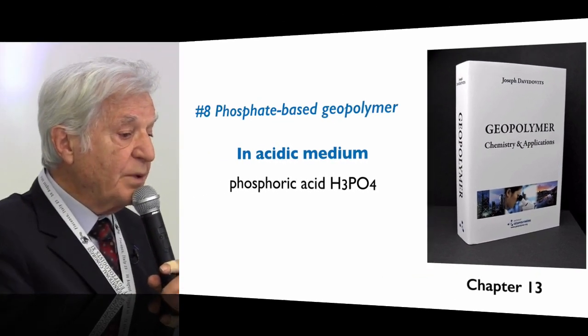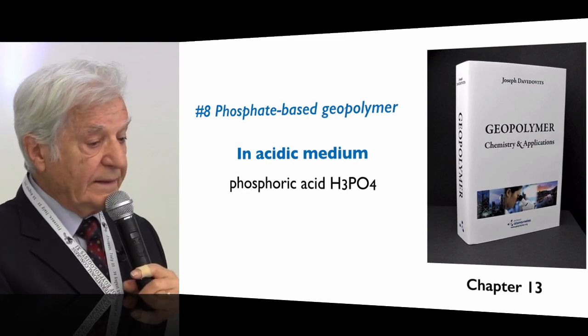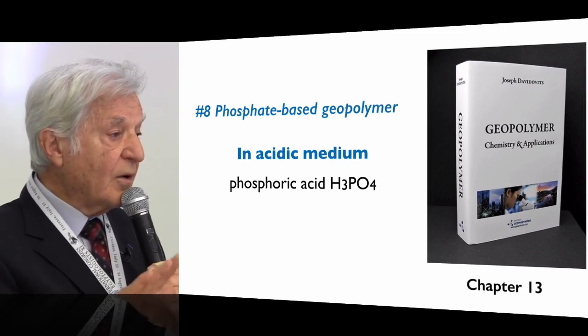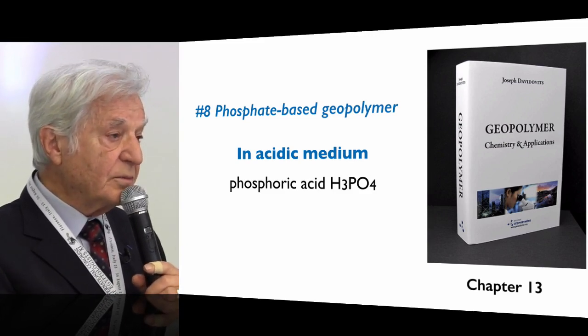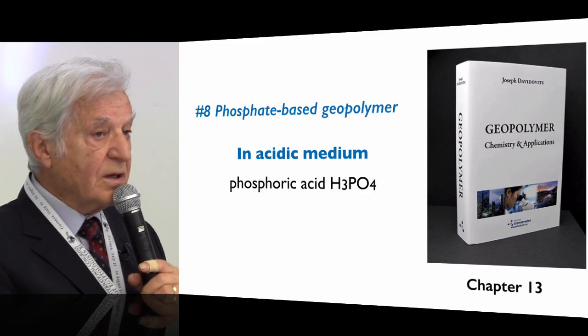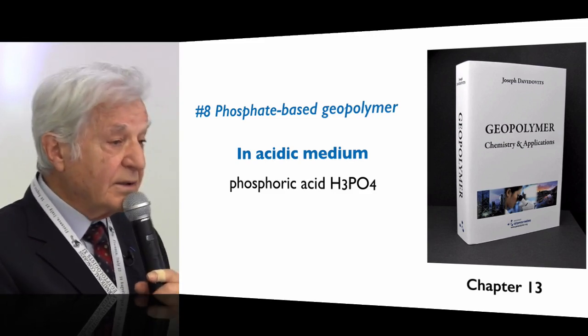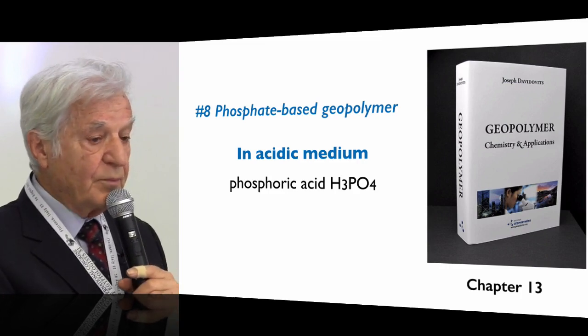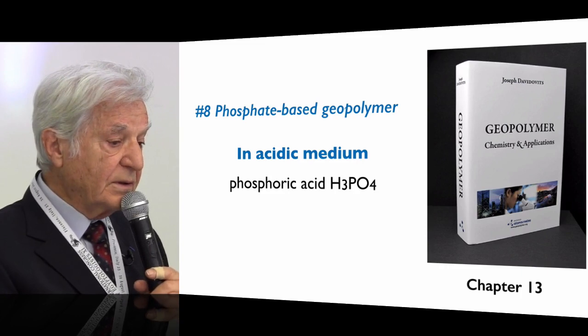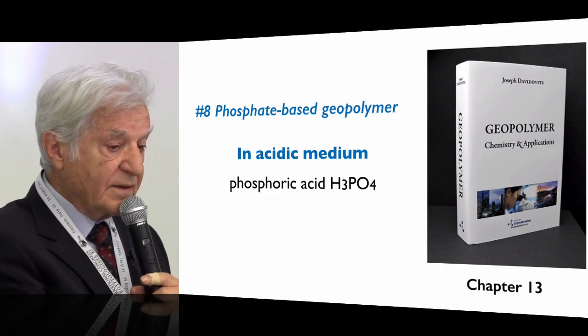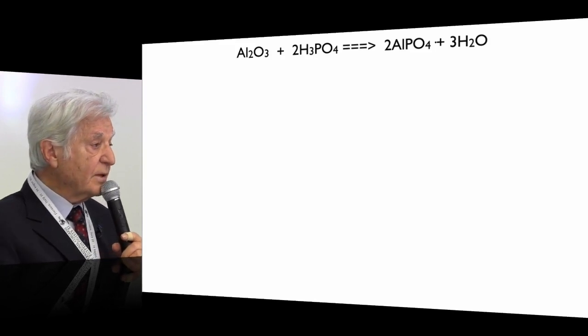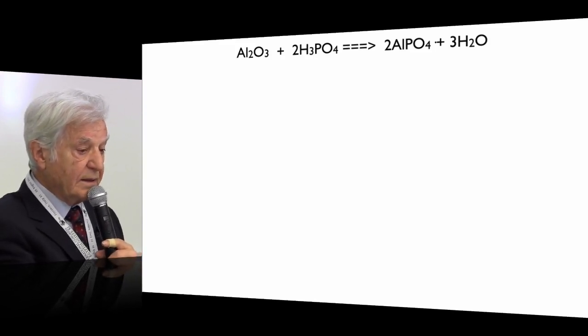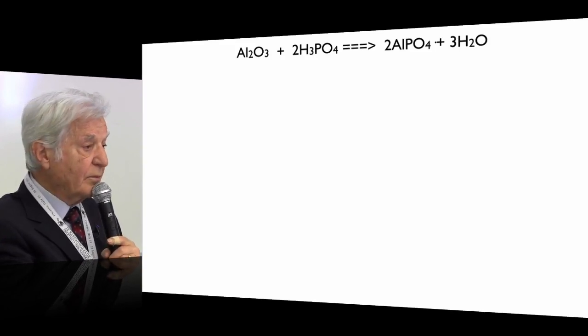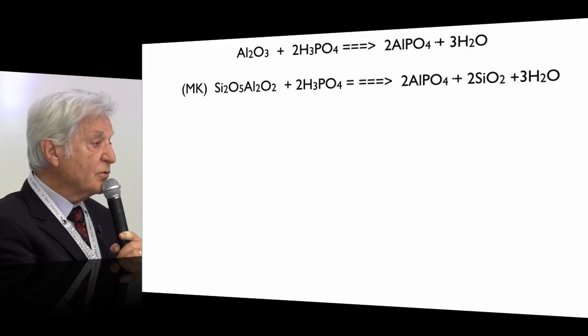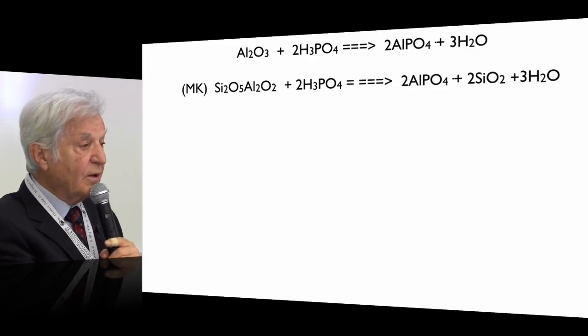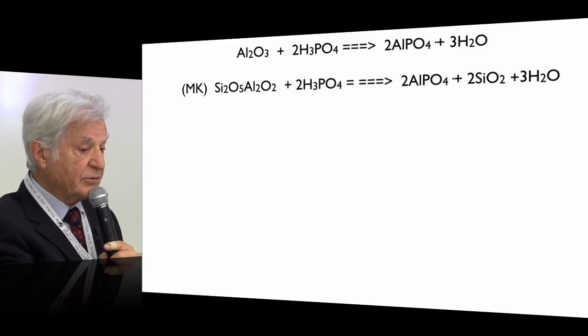So, now topic number 8, that is my second topic. It is phosphate-based geopolymer, acidic medium. I always stated that we have two media, alkaline and acidic. We started with alkaline because the acidic is more difficult to achieve and to implement. But now it has started, essentially with phosphoric acid. We have a reaction with aluminum oxide and phosphoric acid that produces AlPO4, aluminum phosphate, but we have also the same reaction with metakaolin, and we get also aluminum phosphate plus SiO2 in the matrix.